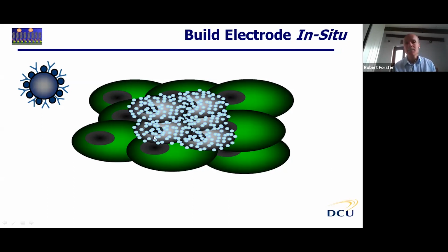Now the concept is that these nanoparticles assemble an electrode in situ. And now the size of your electrode is not 1 nanoparticle, it is the entire conglomerate or aggregate of those particles. And if we get enough particles in there, we can get a conducting path if we're above the percolation threshold. And now we might build an electrode in situ that is many hundreds of micrometers in size.